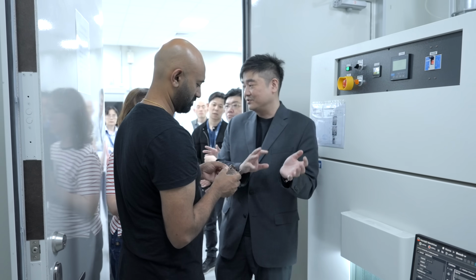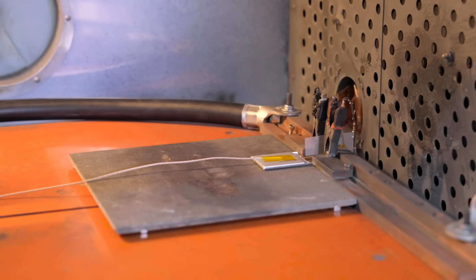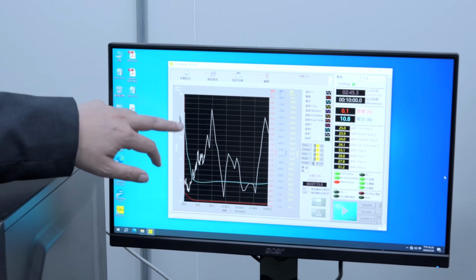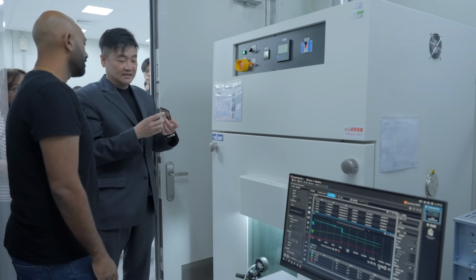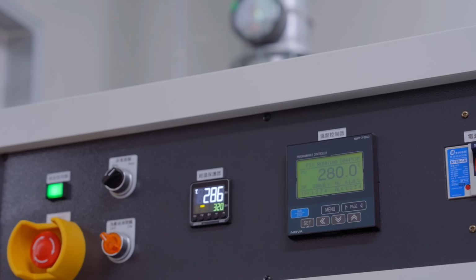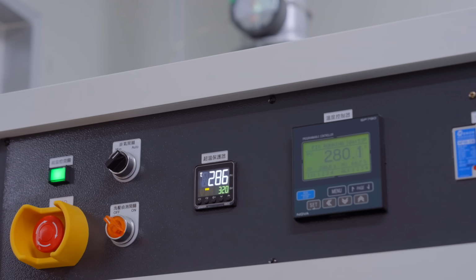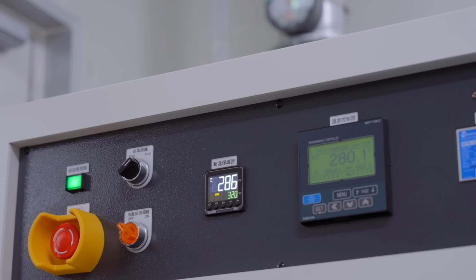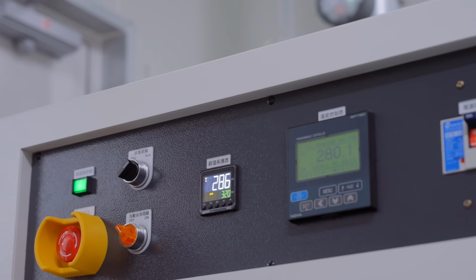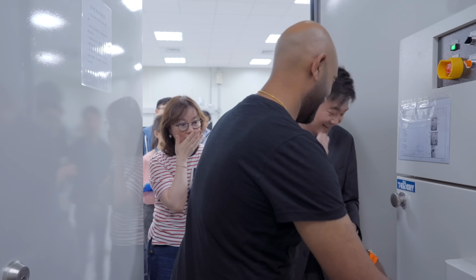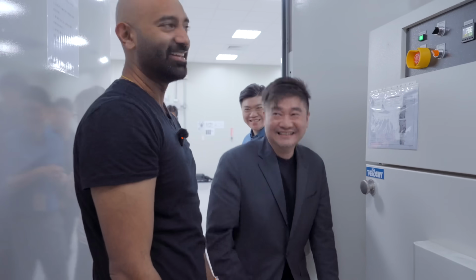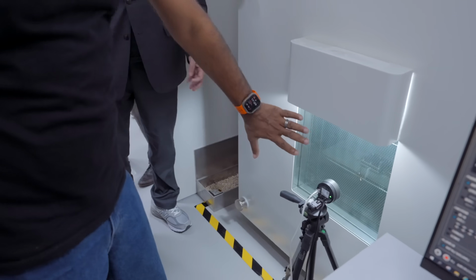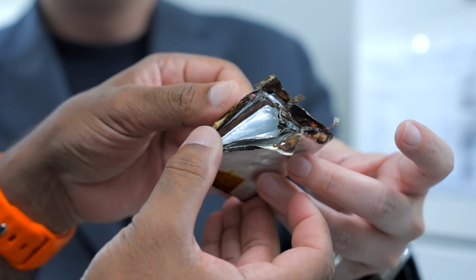In ProLogium's reliability lab at their HQ, I watched as they tested 5 different ways to absolutely destroy a battery. First was the oven test. A live cell goes into an industrial oven that ramps up to 280 degrees C, almost twice the temperature where a conventional battery would already be on fire. I can feel the heat coming off of it, even through all that. Look at the level of insulation, how thick that wall is. This is what 280 degrees Celsius does after over an hour.